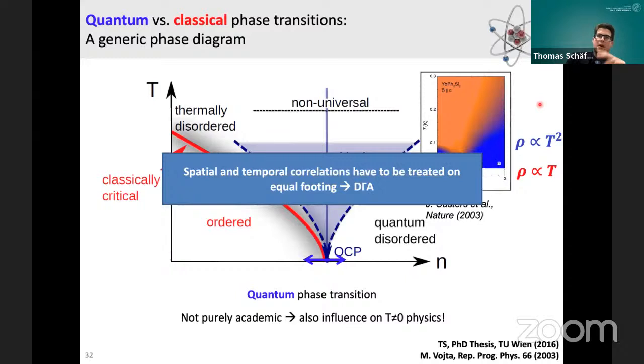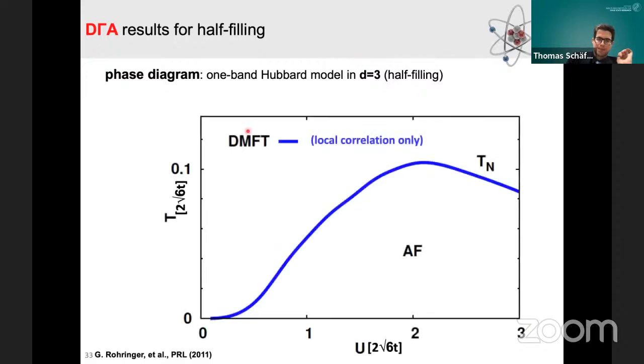Now the question is, coming back to our methods and to our beloved Hubbard model, can this phase transition also show up there? And can we describe this? And we will show that it's indeed possible. So we go now from the two-dimensional system to the three-dimensional system, and we now take into account the magnetism of the model. Again, you have the temperature axis here and the interaction axis. And in DMFT, you indeed get this separation line of a paramagnetic and an antiferromagnetic phase, which is called the Néel temperature.